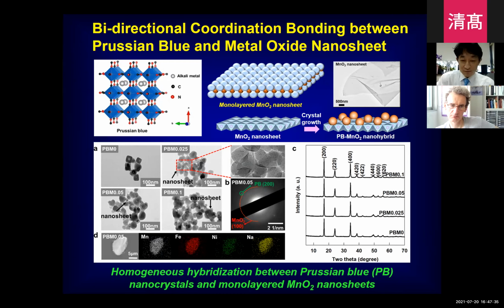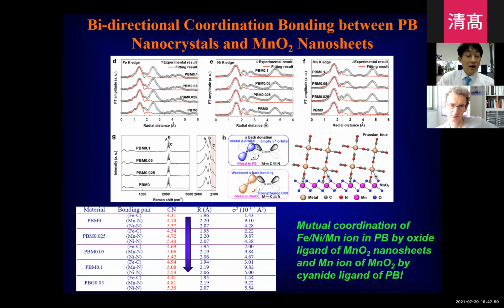Anyway, we can confirm the formation of the homogeneous hybrid material between Prussian blue and the manganese oxide nanosheet from the TEM, electron diffraction and XRD analysis. We proved the formation of the interfacial coordination bonding between the Prussian blue and manganese oxide nanosheet. From the iron, nickel and manganese K-edge XAS analysis, we confirmed the increase of the coordination number. It can be regarded as evidence for the formation of additional interfacial bonding between Prussian blue and the manganese oxide.